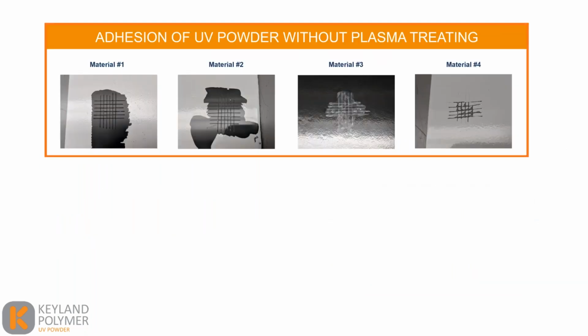So what does this look like on some composites and plastic materials? Well, here we have four different substrates, three of which are plastic. Material 1 is a polypropylene, material 2 is a TPO, 3 is a carbon composite, and 4 is a polycarbonate. And you can see these are all finished without any surface pretreatment, no plasma treating. We're getting very low levels of adhesion, 0Bs across 1 to 3, and then a 1B on the polycarbonate, material 4, which certainly would not be considered acceptable.